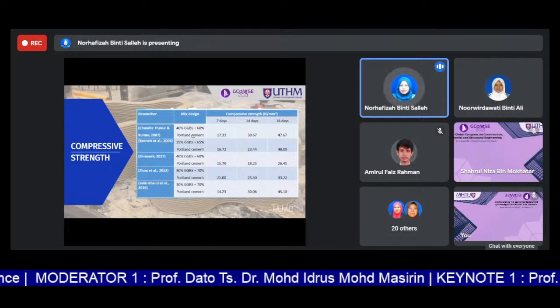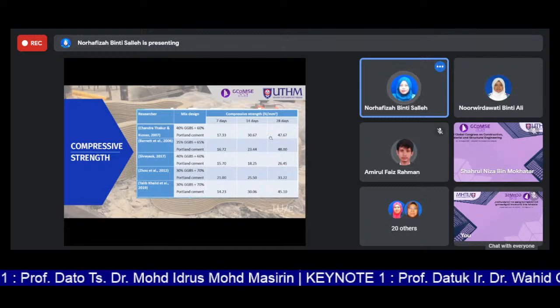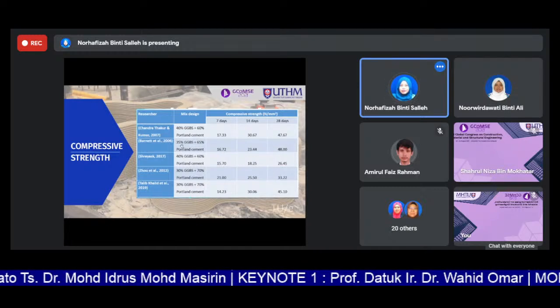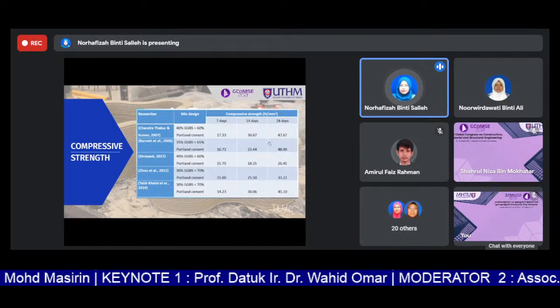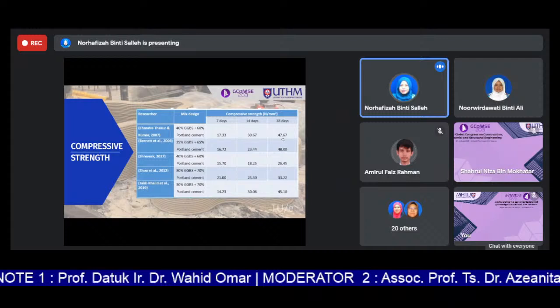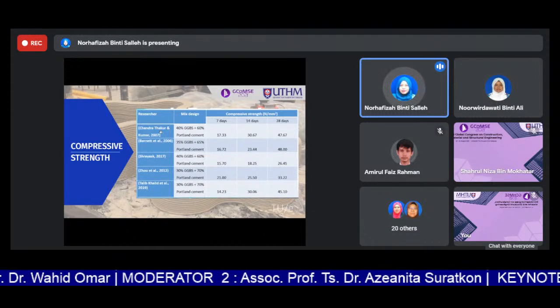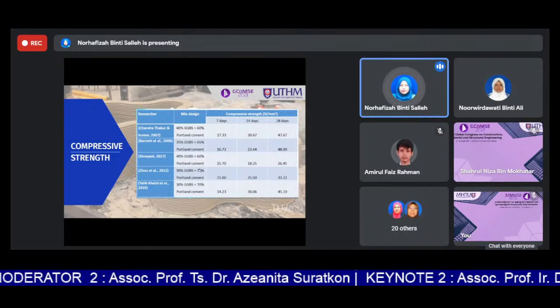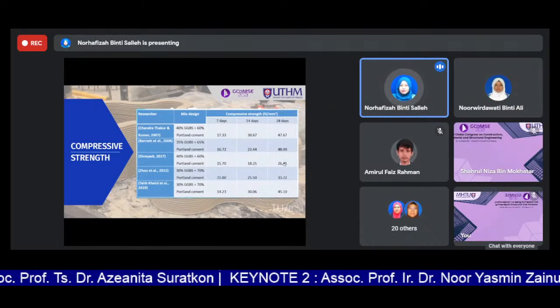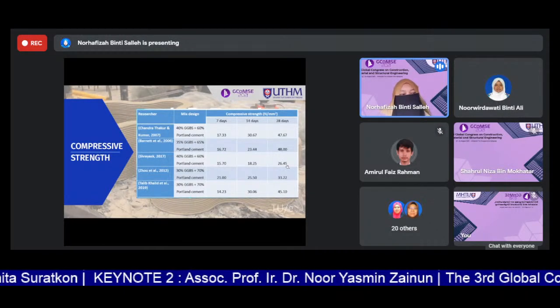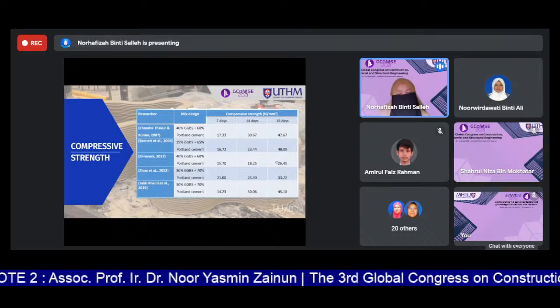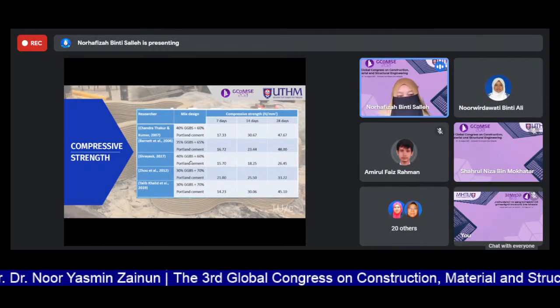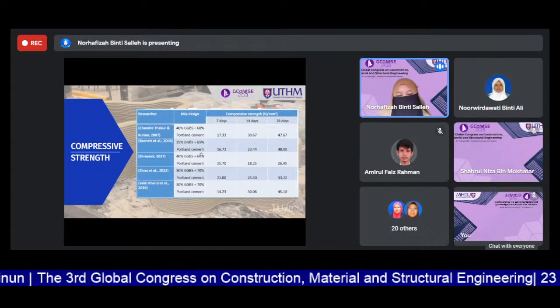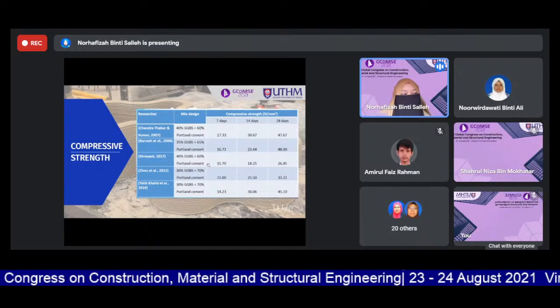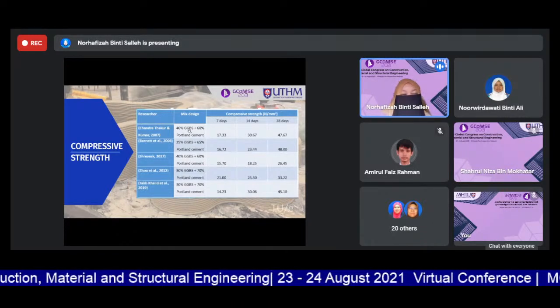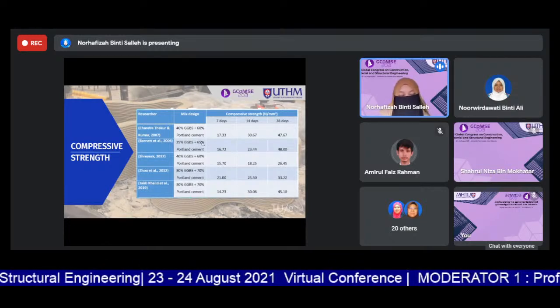Alright, so here is the compressive strength from the several researchers. Here we can see that the combination of 40% and 60% will give 47.67 megapascal. Roughly, we can see that a replacement between 30% to 40% gives around 26.45 megapascal to 48 megapascal strength of concrete. The researchers just replaced directly, without any additional fly ash or others. This is just a replacement between Portland cement and GGBS.